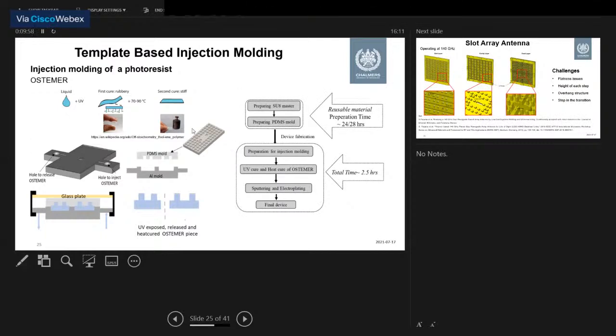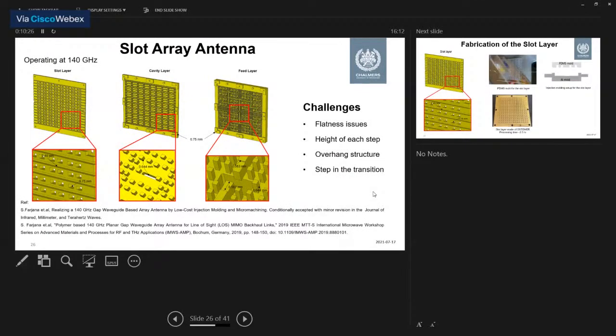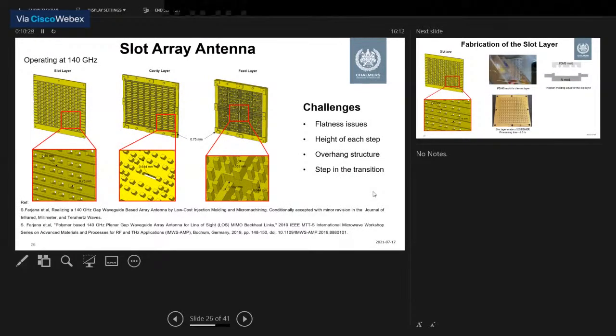So if we consider the preparing of a master and preparing of a mold, it takes 24 to 28 hours. But the benefit is that the master and the mold are reusable. And then for the final device fabrication, we need only 2.5 hours from injection molding to the final device. So based on this method, we fabricate a slot array antenna. It operates at 140 gigahertz. It has 3 layers, a slot layer, a cavity layer, and a feed layer. If you want to read more detail about this antenna, you can check the references.